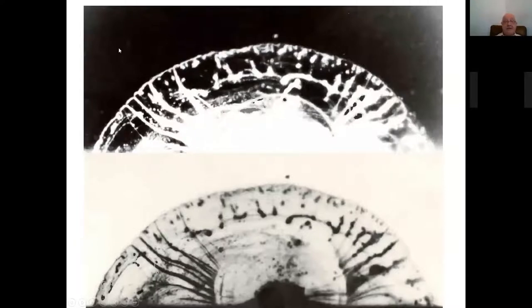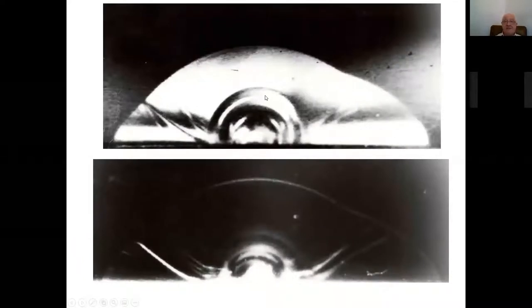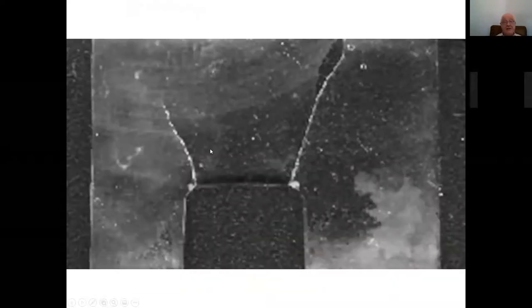So what I'm trying to say is that a three-dimensional growing crack will not be planar, especially if it is in an off-axis, non-symmetric position. Growth will be non-planar, growth will be quite complicated, and at the end, the distribution of the stress intensity factors will be far from constant along the crack front. Another situation is one in which, from the initial crack, you have these large wings towards the ends. Now, getting into the measurements, this was a model in which we had two initial cracks with different initial lengths. One of the cracks grew, the other remained essentially in the same position. So this is what happens in many cases.